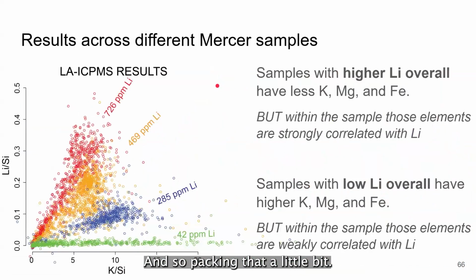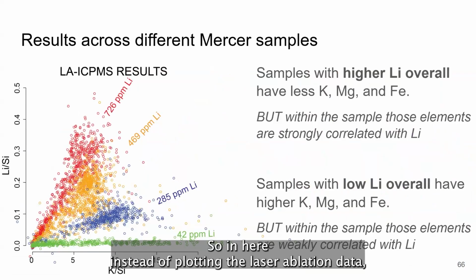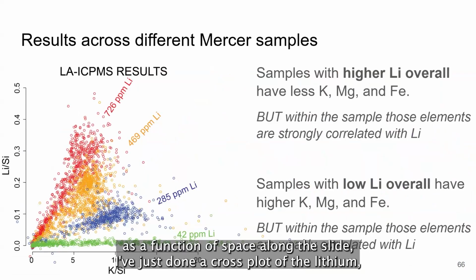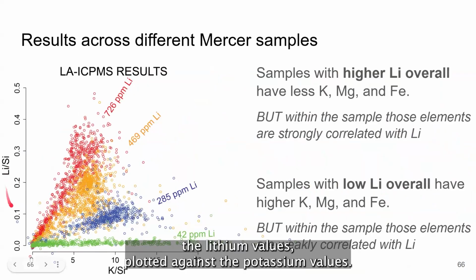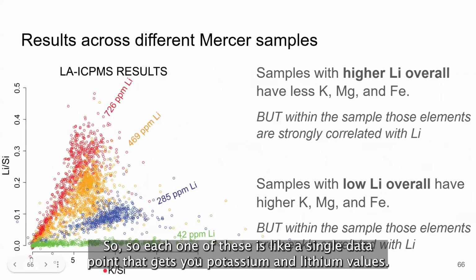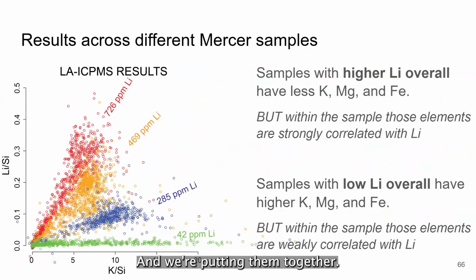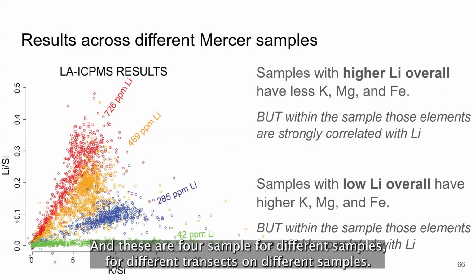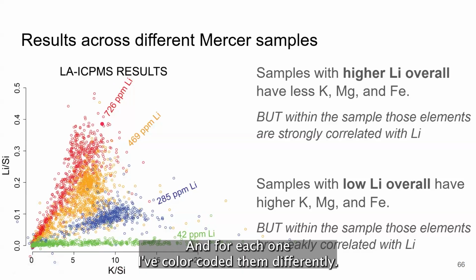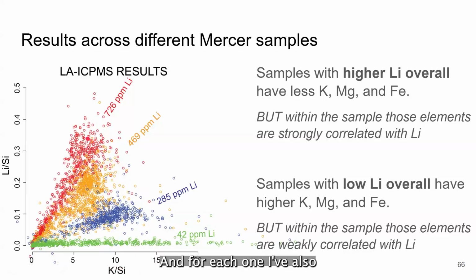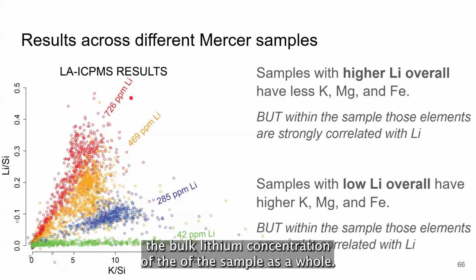And so unpacking that a little bit, in here, instead of plotting the laser ablation data as a function of space along the slide, I've just done a cross plot of the lithium values plotted against the potassium values. So each one of these is like a single data point that gets you potassium and lithium values, and we're plotting them together. And these are four different samples, four different transects on different samples. And for each one, I've color-coded them differently. And for each one, I've also superimposed here the bulk lithium concentration of the sample as a whole.